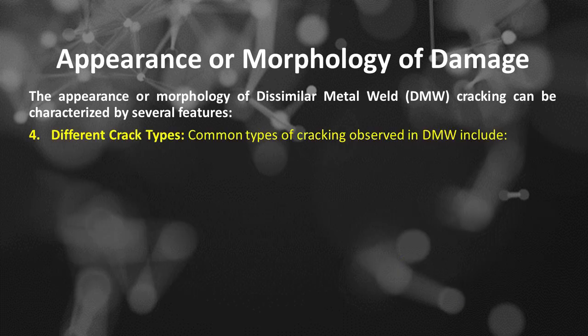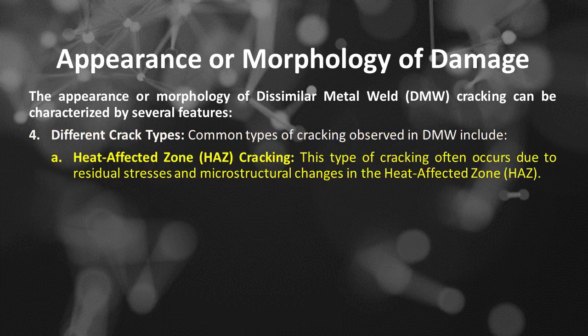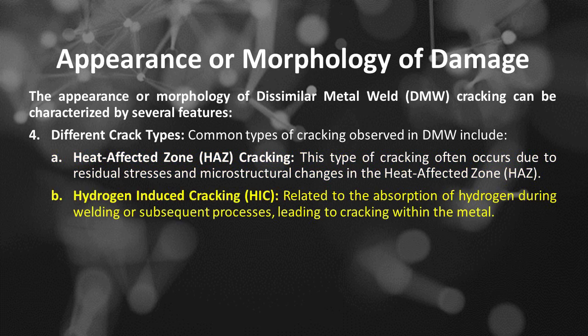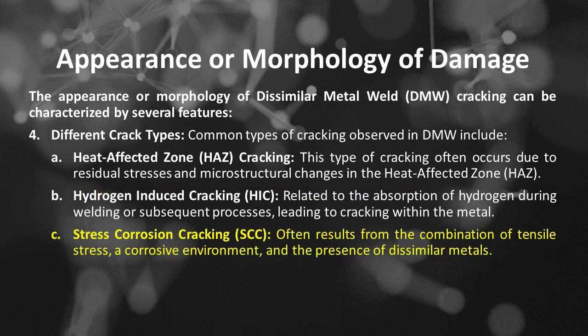Number 4 is different crack types. Common types of cracking observed in DMW include: the first is heat-affected zone, HAZ, cracking. This type of cracking often occurs due to residual stresses and microstructural changes in the HAZ. The second is hydrogen-induced cracking, HIC, related to the absorption of hydrogen during welding or subsequent processes, leading to cracking within the metal. The third is stress corrosion cracking, SCC, which often results from the combination of tensile stress, a corrosive environment, and the presence of dissimilar metals.